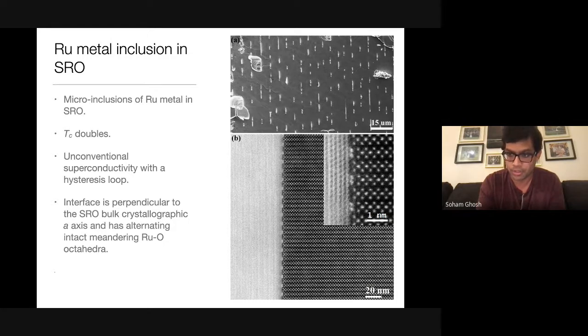But the bottom picture is extremely detailed. That scale goes all the way down to 1 nanometer. The white dots you see are actual images of real atoms. What you are looking at is the electron shining out of the electron cloud of the solid atoms themselves. In this picture, the shiny dots are ruthenium metal, and the gray or black part is strontium ruthenate, the oxide. Now, if you zoom into it, in image B, the inset, you will see that you have a periodic